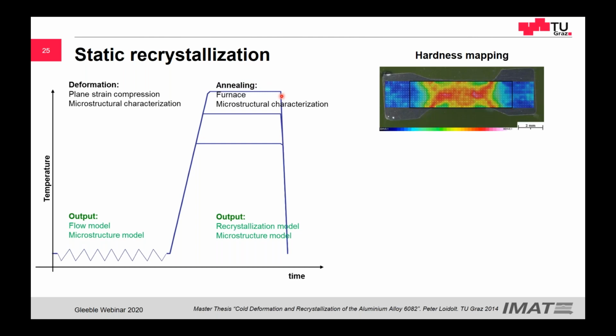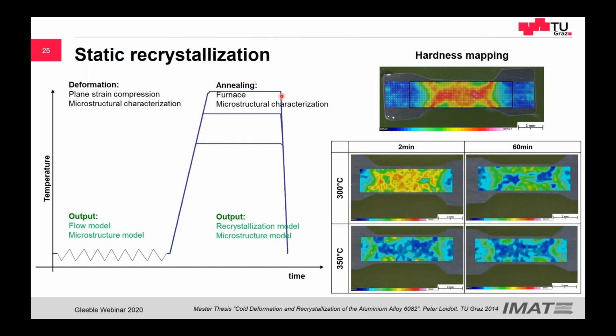So we use these hardness maps, which are very easy, and we like them because of it, to characterize the static recrystallization. And as you can see, this is the cold deformed piece, very small sample, and then we heat it up in a furnace. And you may ask why you didn't heat it up in the Gleeble. And I would say because we have seen that recrystallization of cold deformed parts in the Gleeble happens much faster than in the furnace. There are some publications not done by me, but by some other colleagues from Lyon, Damien Fabrègue is one of them, and a colleague in China also did a publication about it, showing that you can accelerate the recrystallization if you have very large stored energy by electrical transport of energy. It is a very interesting paper from my colleagues.